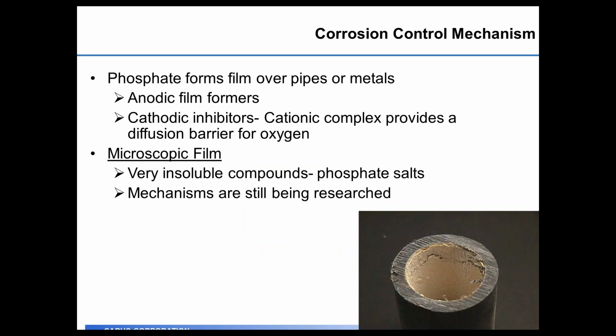Specifically, corrosion control mechanism is that we know phosphates form films over pipes or metals out there in the distribution system. Specifically, phosphates are anodic film formers in the distribution system. They're also acting as a cathodic inhibitor in addition to the anodic film former, providing a barrier between the metal surface and the oxygen in the water itself. The research has shown that there's a very microscopic thin film that forms on the inside of the pipe, and these very insoluble compounds, phosphate salts, form on the surface. Even today, we're still doing research at AWWA and other national organizations to see how these products work in the distribution system based on the varying water quality we have across the U.S. But knowing that we form this film that prevents metals from dissolving from the pipe surface into the water.